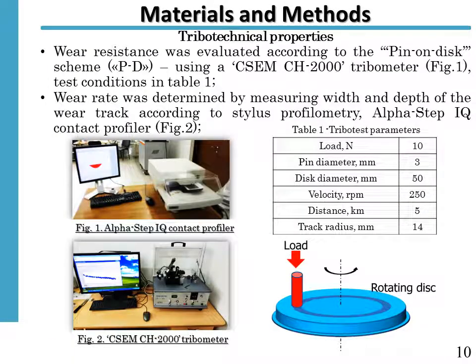Since we are talking about wear resistance, we used a tribometer of this particular type that employs a pin on disc scheme. In order to estimate wear rate or wear intensity, we use a stylus profilometer. And here on the right you see the parameters for the testing. That was the principle for how to estimate the wear of a polymeric specimen while it rotates over the polymeric counterpart.